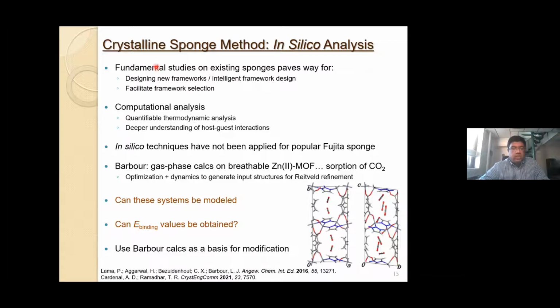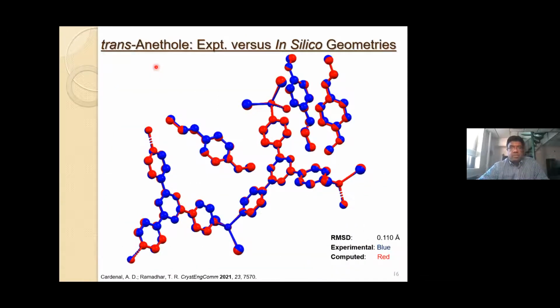And what we wanted to do was to initially do some geometry optimizations and then be able to calculate the binding energies of various target molecules inside of the crystalline sponge. We were able to do DFT-D, or basically density functional theory calculations with dispersion corrections, in Materials Studio. And so I'll just talk about one example, which was the first case that we did, trans-anethole. We were able to do geometry optimizations on this system in Materials Studio, and we did it in the gas phase.